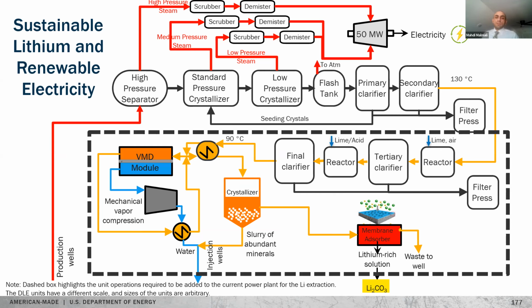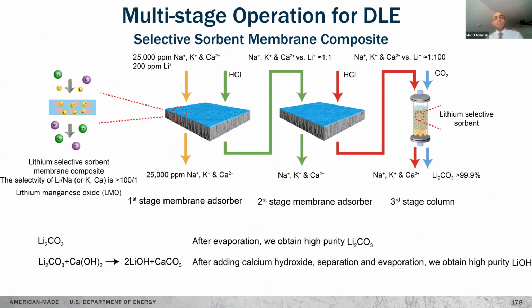Next, please. So in the next step, what we do is we have a 3-stage absorber. The first two are membrane absorbers. Essentially, we are providing very, very porous structure of the membranes with accessible absorbers, and the brine is getting in, and at this point, based on the reports available, we have selected a selectivity of 1/100. Most of the reports are providing up to 400. We wanted to be targeting some of the low numbers. So it's 1/100. In the first stage, we are getting almost lithium 1-to-1 with other divalent and monovalent ions.